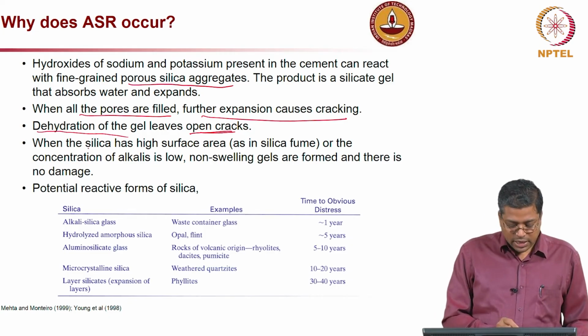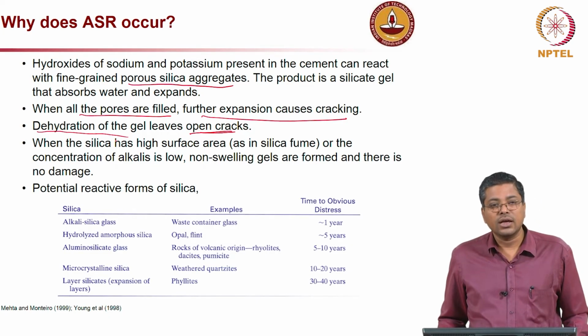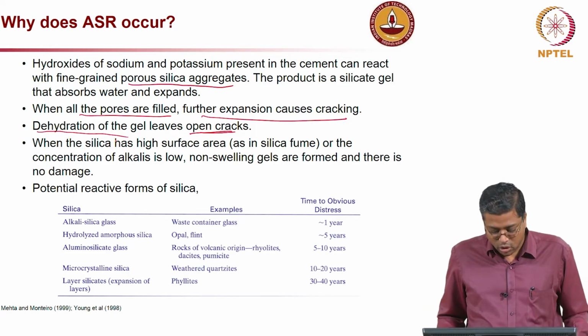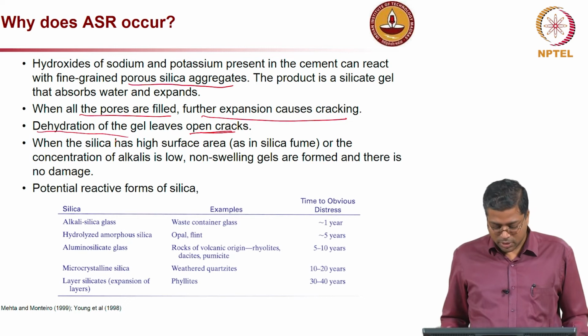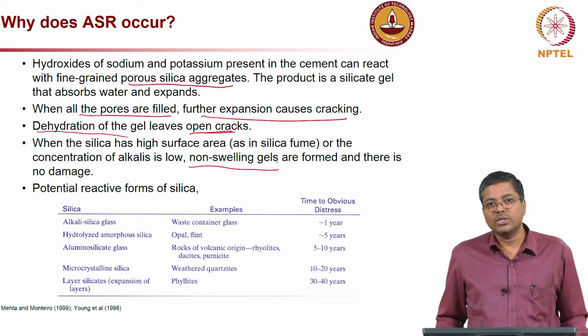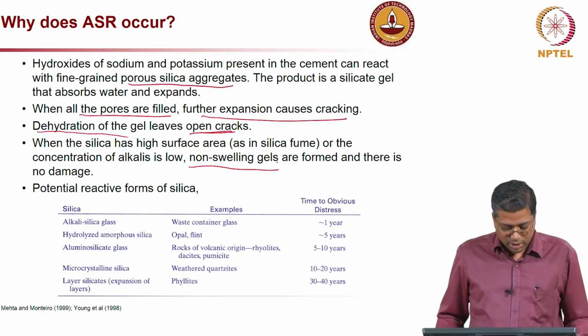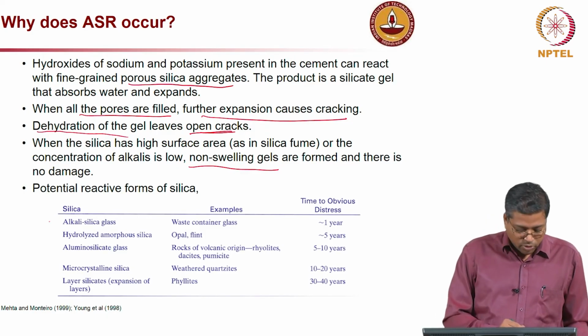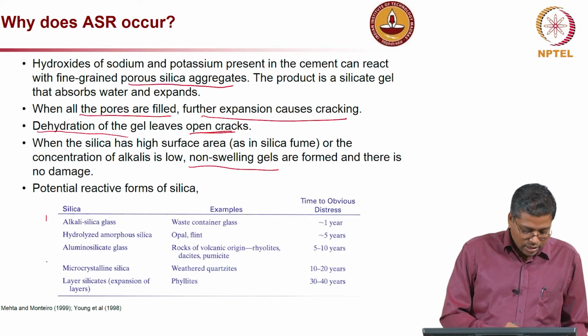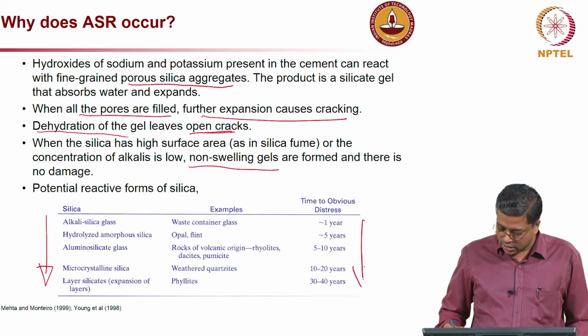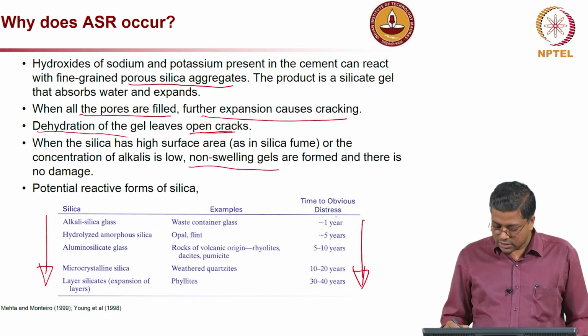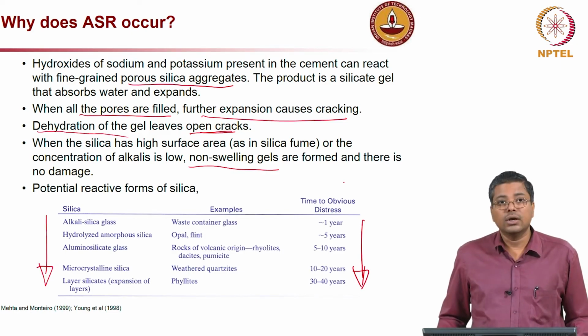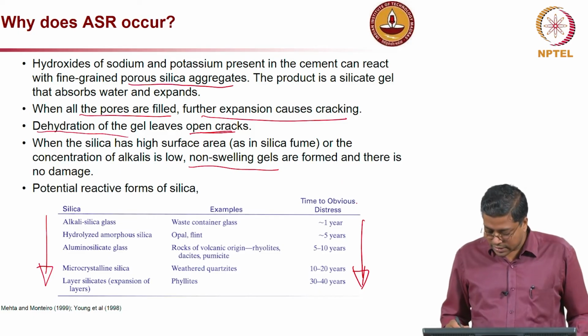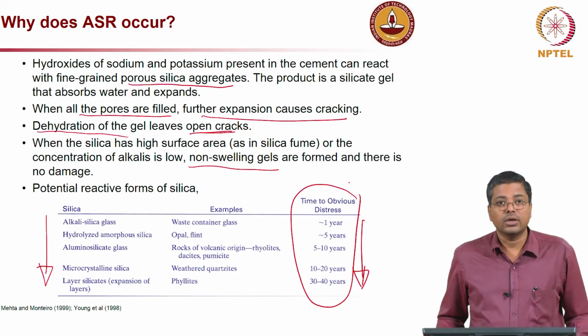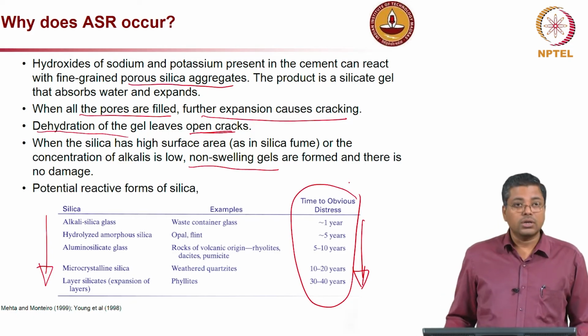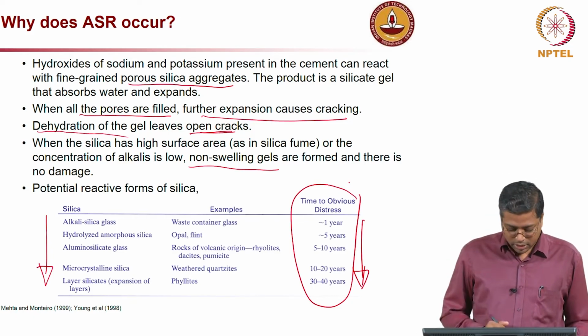Now, when silica has high surface area and the concentration of alkalis is low, then you will have some non-swelling gels, which may not induce really significant damage. So, let us also look at which type of silica can be selected. In this table, as you see on the right side, it indicates if I use a particular type of silica, what is the expected life for that structure. As you go down the table, you get better and better aggregates.